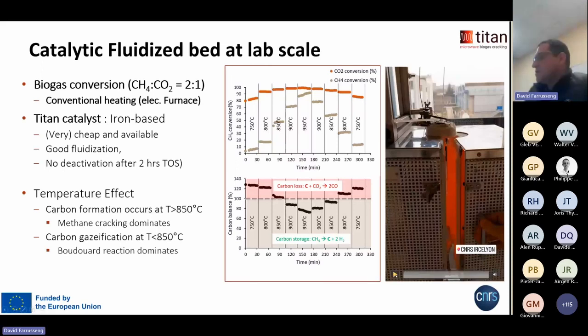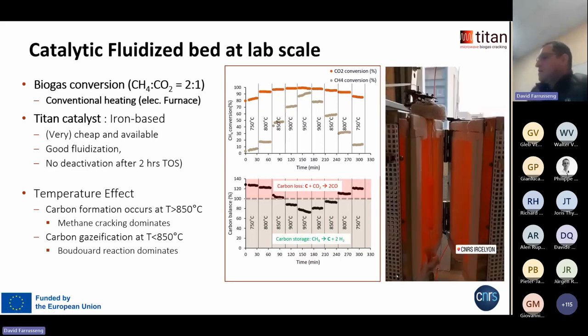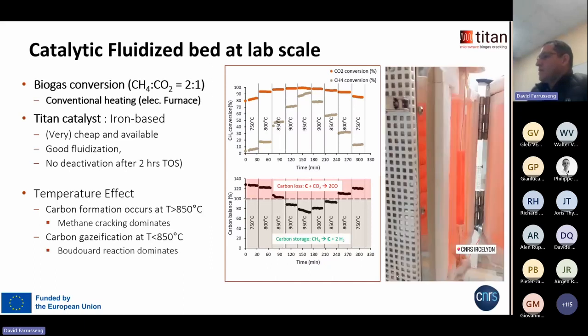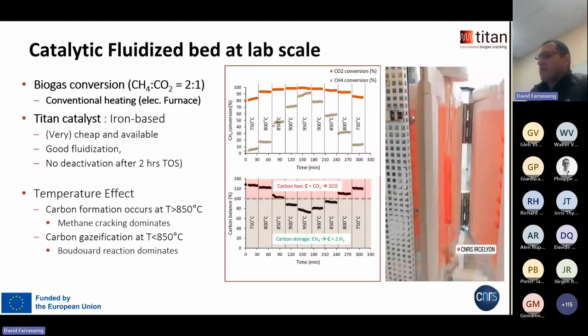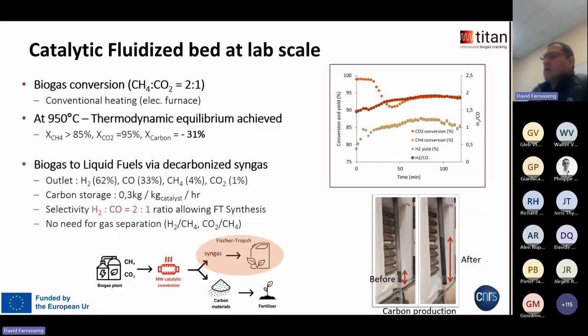So you can see here on this video, I hope you can see it, a fluidized bed working at 900 degrees C with the iron-based catalyst, very hot, in fact, like a lava. And we do not see deactivation after 2 hours on stream, even maybe 3. Actually, we achieve thermodynamic equilibrium, and we produce about 30% yield of carbon, which at the end of the day would make an outlet of 60% hydrogen, 30% CO, and very little methane and CO2. So basically, you will produce a syngas with a 2-to-1 ratio, and at the same time you will produce carbon at 0.3 kilograms per kilogram of catalyst per hour.